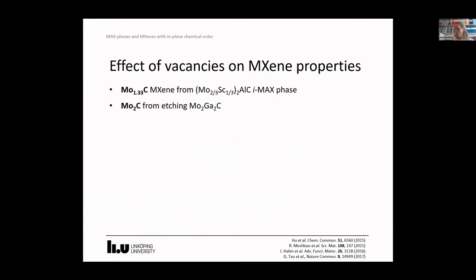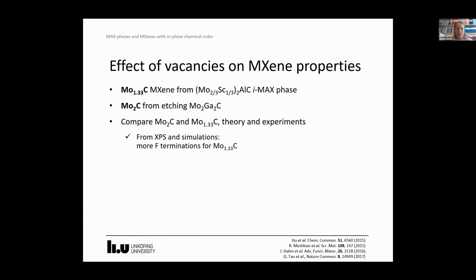Also, for the Mo MXenes, we can study the effect of vacancies on the MXene properties, because we have the Mo MXene from the i-MAX, and we also have the Mo2C MXene from etching of the Mo2Ga2C. If we compare these through theory and experiments, we can see from XPS and simulations, for example, that the vacancy MXene tends to have more F terminations. This could be because there are fewer electrons from Mo available for bonding in the vacancy MXene, which could suggest a preference for fluorine terminations.